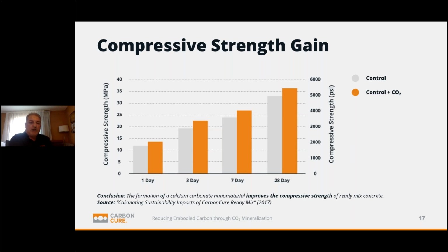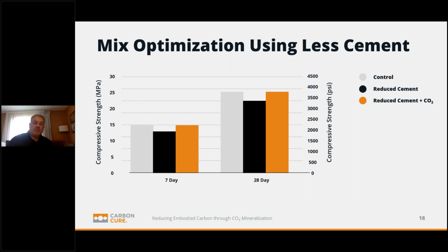So if you're designing a 25 MPa concrete, you don't need your 25 MPa concrete to be 10% stronger. What you want to be able to do is to have the optimal environmental impact. So what we'll do then is take out a portion of that cement. We'll obviously continue to optimize the dosage of the CO2 and then try to deliver that optimal 25 MPa concrete with the most reduced environmental impact we can.